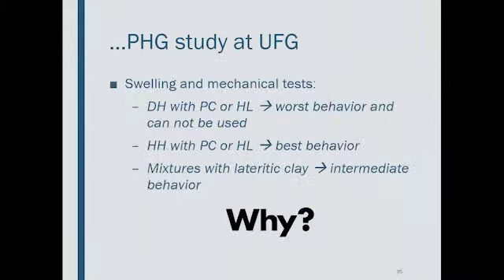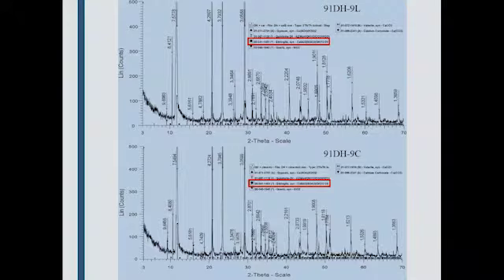Then you can see that with the swelling and mechanical tests, the dihydrate type presents the worst behavior. Maybe it's not good to use for this purpose. But when you transform to the hemihydrate type, you get the best behavior. And mixtures with this material with lateritic clay presented intermediate behavior. But for now, we cannot explain why this difference of behavior occurs. For this, it's important to take a look at X-ray tests and SEM images.